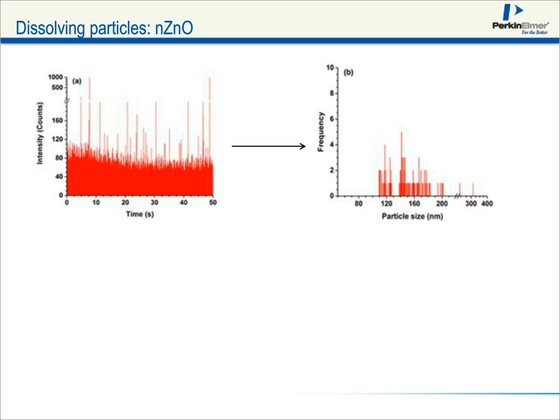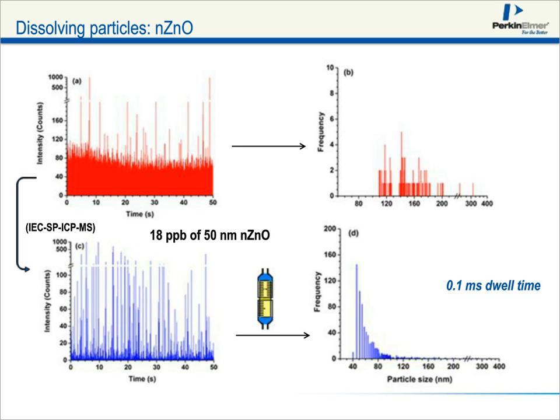When you run that through the IEC column, the ion exchange column, you can see that we are able to distinguish our 50 nanometer. Now I've cheated a little bit here because we're also using these very low dwell times, or short dwell times, that Shadi was talking about. So that's doubly helped us. That's been able to really give us an additional benefit in getting to these really highly dissolving particles and probing some of the information. Now that was done in water, in Milli-Q water.